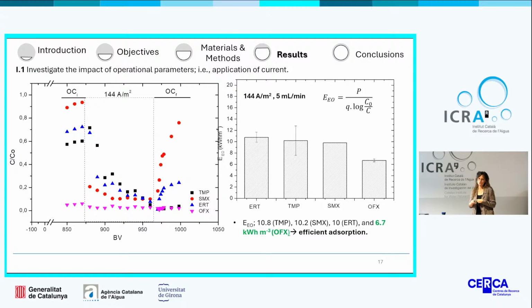Then, when the current was again switched off, antibiotics gradually increased again to values lower than the open-circuit initial conditions, which means that we are degrading our contaminants and also regenerating the sponge. On the other hand, it's important to mention that the fact that the antibiotics didn't achieve the initial condition is probably a consequence of the capacitance of the electrodes.